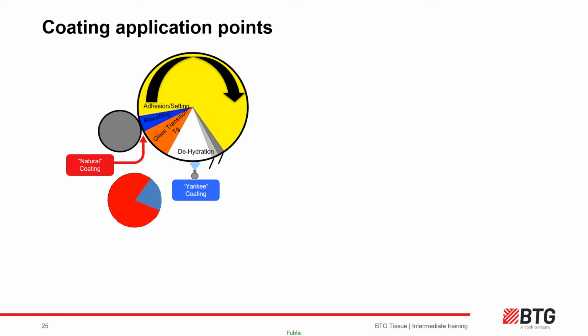At the nip, the sheet is approximately 40% solids, meaning 60% backwater, and so with a level of process contamination. Some of this contamination is removed at the press through the felt. The coating products are predominantly cationic at this point, which means they are positively charged and tacky. The contaminants are anionic or negatively charged, meaning there is a natural attraction into the coating matrix.